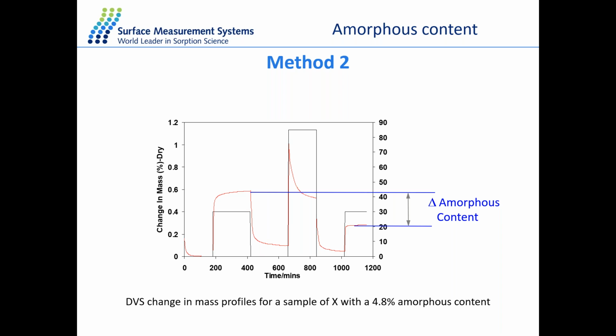So what solvent should I use? More often than not, that material is being made amorphous using a solvent. Could be water from freeze drying, or could be two solvents, a co-solvent and anti-solvent, from crystallization or from spray drying. So those solvents are the ones that we are going to test first to see if they can change the amorphous back to the crystalline form. Usually the solvent that is able to form the amorphous phase is also the one that is able to give you enough energy to move to the crystalline phase.